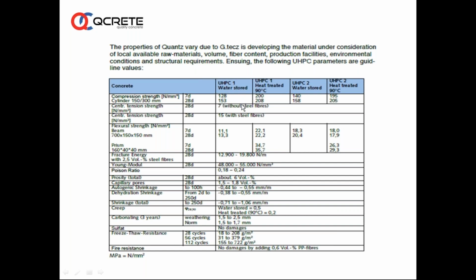So you can see the capillary pores are less, shrinkage is less, and then creep is less, carbonation normal, sulfate resistance no damages. So fire resistance also is given, means the product has been defined and designed for even high fire resistance.